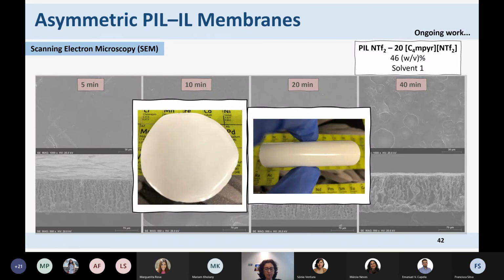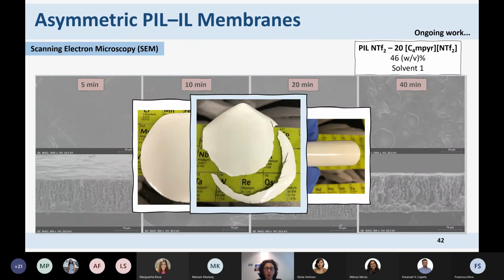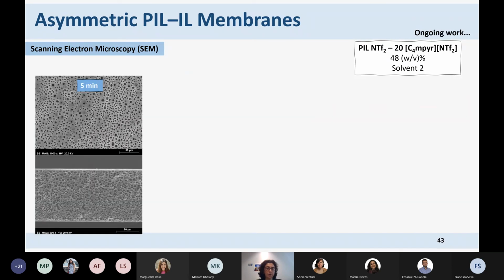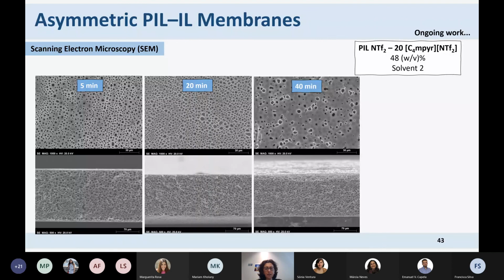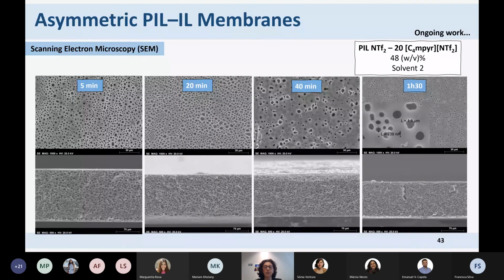What happened is that this membrane seems very nice. These are the membranes. They are not transparent anymore. They have color, but they are very fragile and they break as you touch them, as you manipulate them, they break inside of the apparatus. Now, if we look at the other example with another solvent, we can see here that we have porosity on top and in the bottom, inside of the membrane, this is a cut.